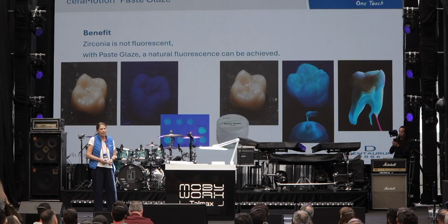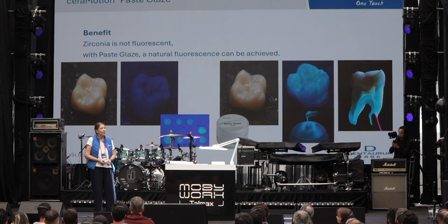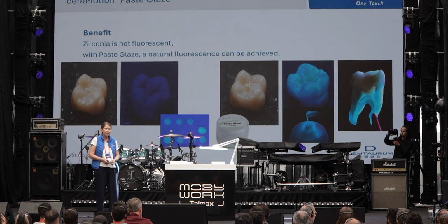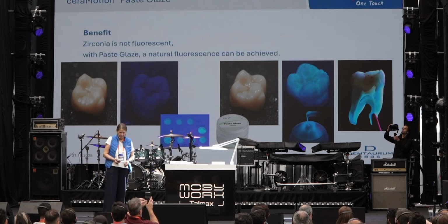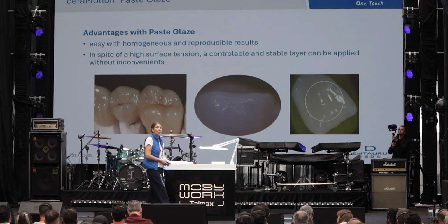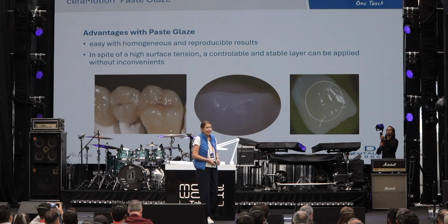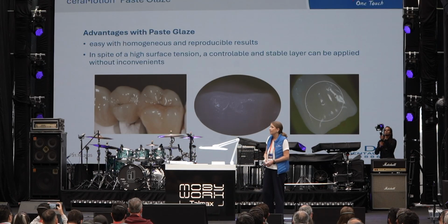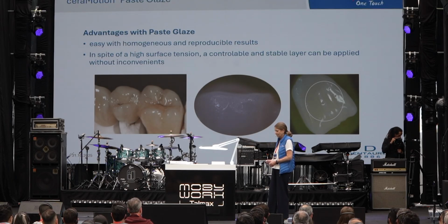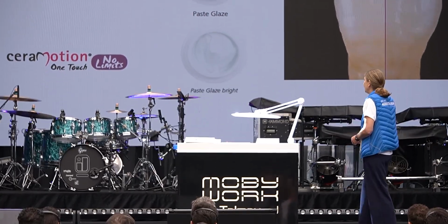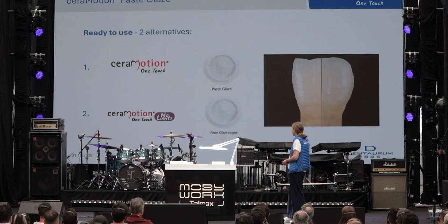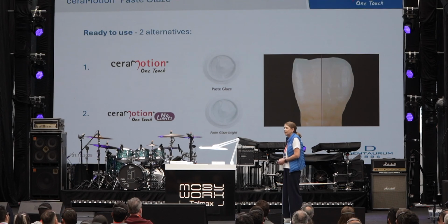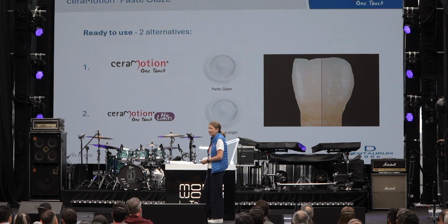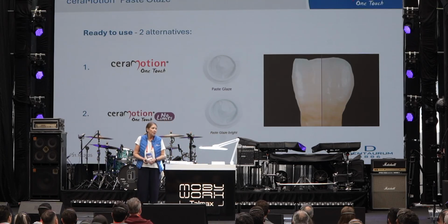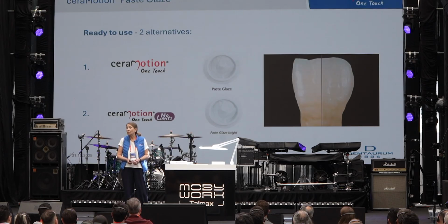Another benefit is that we increased the fluorescence in these materials. Zirconia is not fluorescent at all, so we have to add fluorescence to the surface. Zirconia also has a very high surface tension, but this paste glaze has very good wettability on zirconia. We provide two glazes. One is the CeraMotion paste glaze in the first set, the One Touch set, and the other one is in the No Limits set. The paste glaze bright in the No Limits set has a slightly higher turbidity than the other one. So we recommend the bright for the bright colors and also for the bleach colors.